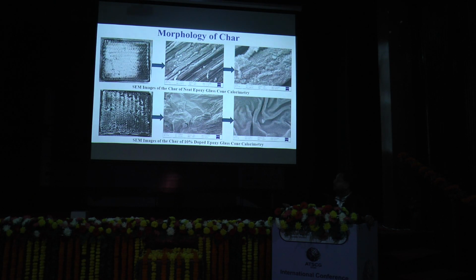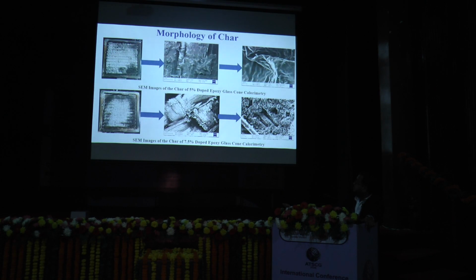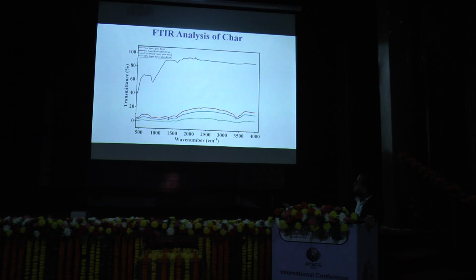This is the morphology of the char after the burned sample. Here we can see that the 10% doped composite shows more char formation compared to the neat composite. We observe a similar pattern in the 5% doped epoxy composites and 7.5% doped glass composites.